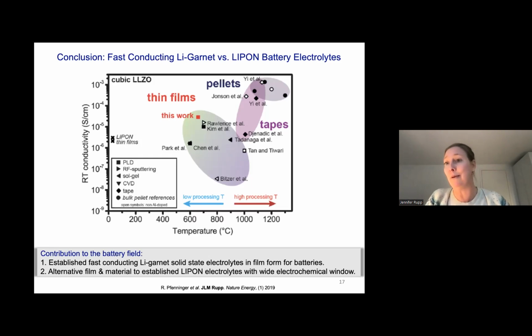So this is all quite beautiful and academically quite nice, but what I show you here is not really helping the world. And this is why. What I liked about it is we demonstrated the concept that you can actually make lithium garnet films as nanostructured chemistries, which hasn't been done as successfully before. However, the method we chose is far too expensive. It's a vacuum chamber. You can't really upscale the area. It's very expensive to do. So it's good academically, but it's not really good for introducing that into other systems.